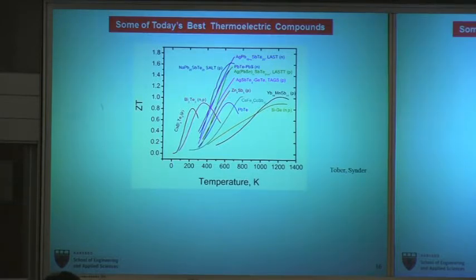So this is our friend ZT as a function of temperature, and because this is done by physicists, it's in Kelvin. There are two things to note about this. One is these curves typically rise, reach a peak, and then decrease again. That's because of the way in which the electron conductivity increases with temperature. So you'll see that there's a whole range of materials that have ZT of less than 1.